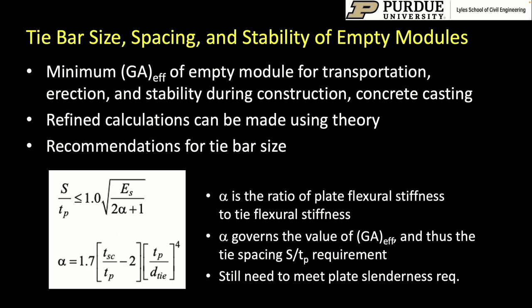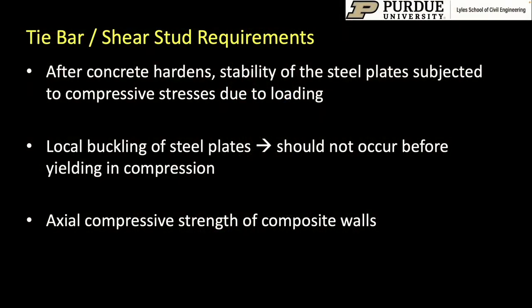So when the AISC 360-22 specification comes out, you will see that it provides a tie bar spacing divided by plate thickness limiting equation, which is based on the shear stiffness of the individual empty module, which is a function of the flexural stiffness of the plates divided by the flexural stiffness of the tie bars. It was pretty fascinating. But after the concrete hardens, the stability of the steel plates follows a slightly different behavior.